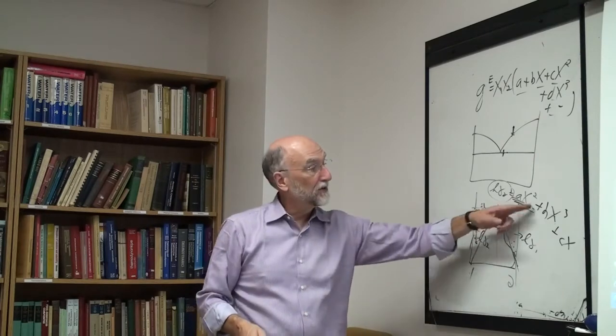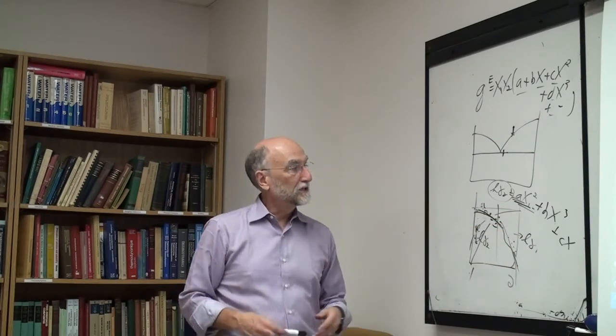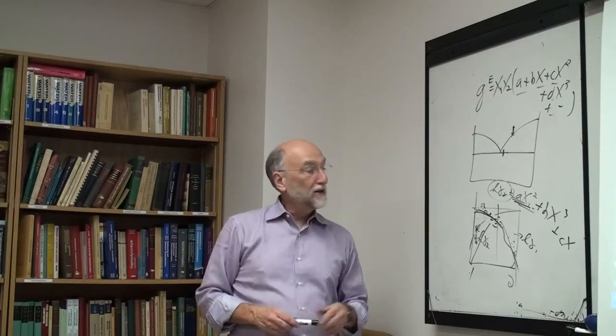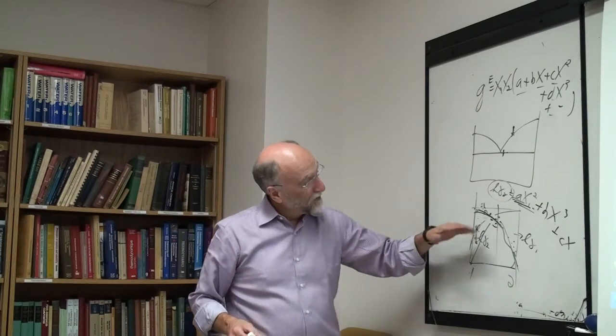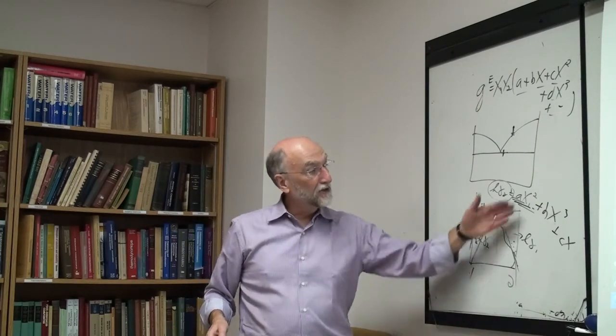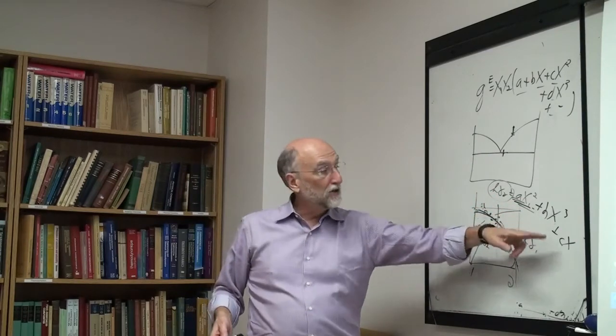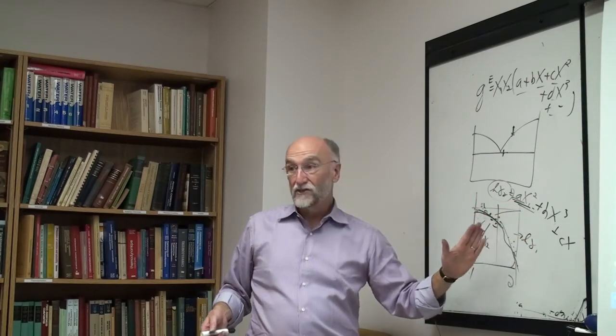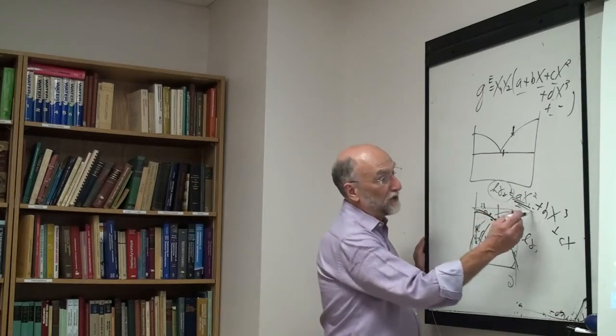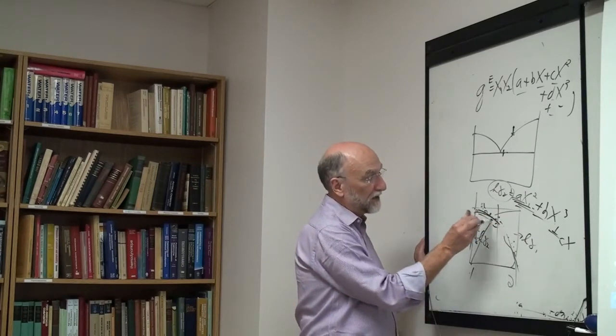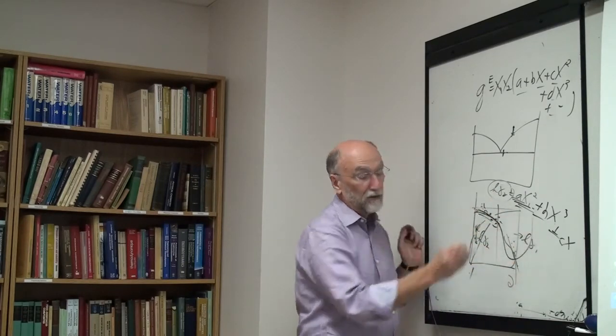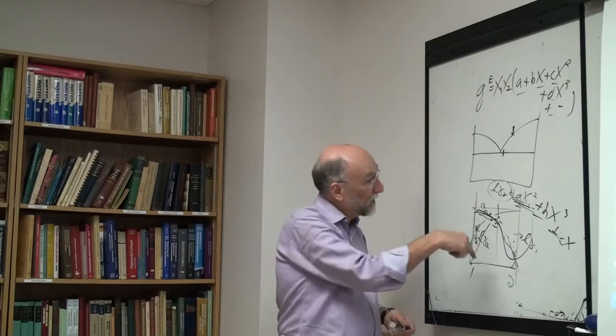Because these are really empirical terms. They don't really have much physical significance. With too many terms, not only do you get a wiggle, but when you try to extrapolate, the thing can go crazy. So the more terms you use, the smaller the distance that you can extrapolate. You try putting in 4 terms and you get a lovely fit here, and then extrapolate it and it can do something crazy. You really have to plot the thing out to see what's going on.